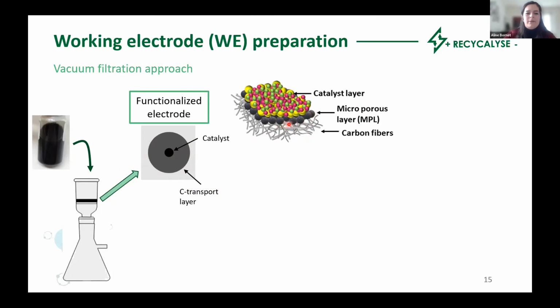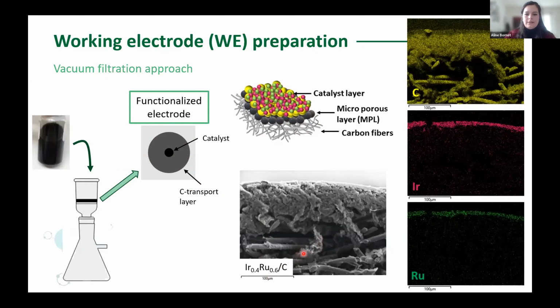We have the carbon fibers of the transport layer, and this is the porous network. On top of it, we have the microporous layer, MPL, and this prevents the penetration of the catalyst into the fibers, and on top of it, the catalyst itself. And in reality, it looks exactly the same, and we can see it in this cross-section SEM image. We can see the carbon fibers, the MPL, and on top of it, forming this brighter layer, this is the catalyst. And we performed some EDX mapping, and we can clearly see that iridium and ruthenium are forming a homogeneous layer on top of the MPL, and they are not all over the transport layer.